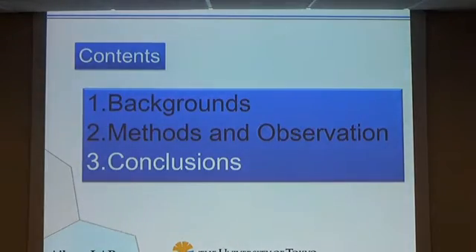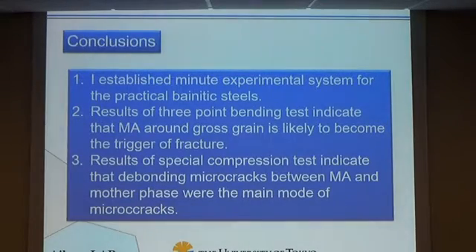And the last, conclusion. First, I established an experimental system for the practical bainitic steels. Second, results of the three-point bending test indicate that MA around the coarse grain is likely to become the trigger of fracture. Third, results of the special compression test indicate that debonding microcracks between MA and bainitic ferrite were the main mode of microcracks.